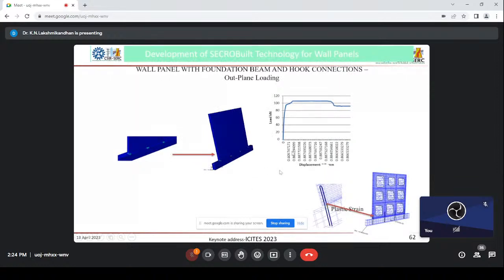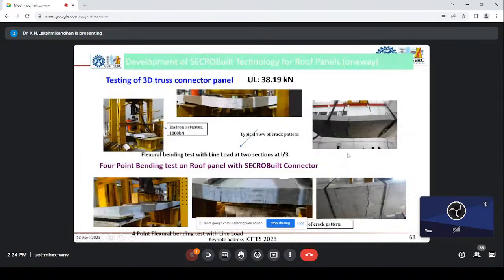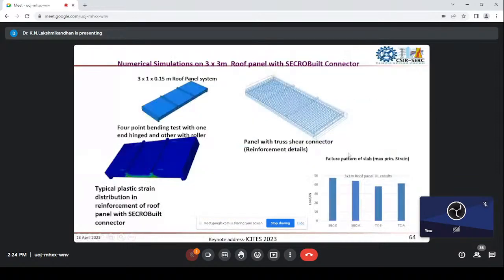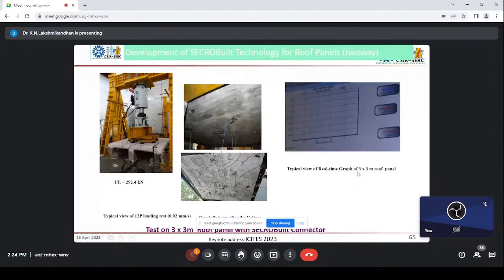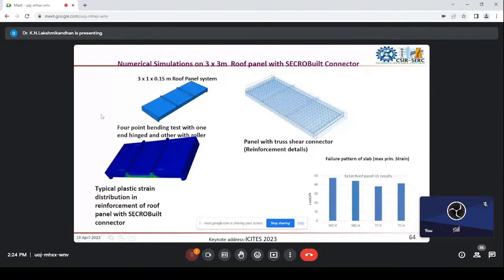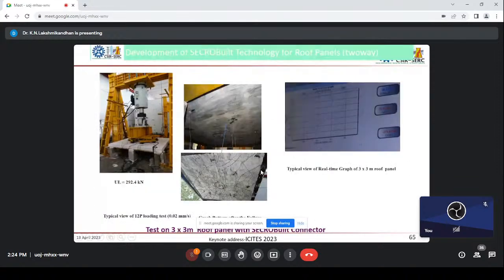Similarly, this is a typical behavior of the interface, and this is the typical behavior of the structure under 2-point loading. Normally these slabs are useful for one-way slab construction, and we wanted to develop a two-way slab. So we developed a two-way slab, and this is the crack pattern. If you see this, everywhere the cracks are in a radial pattern, and the cracking is uniform. Even though the loads are applied here, we applied the load at 12 points as point loads.